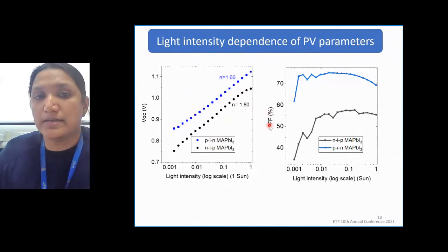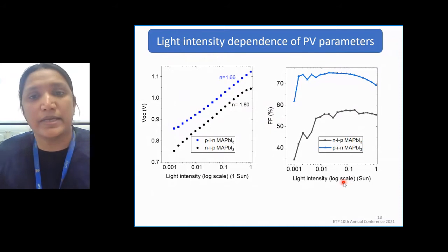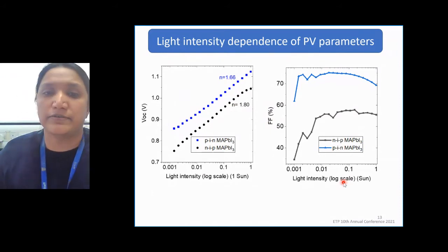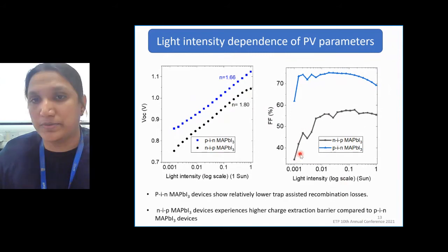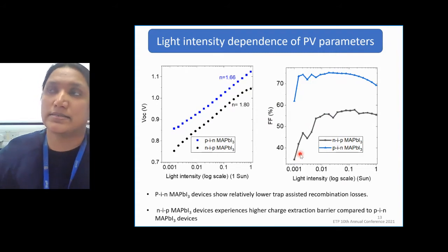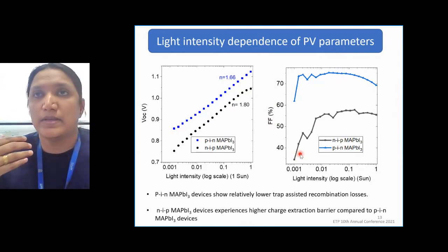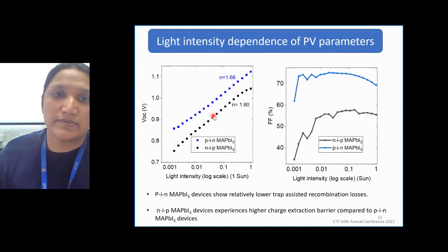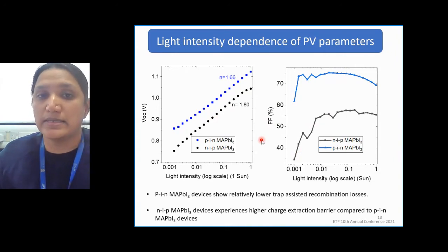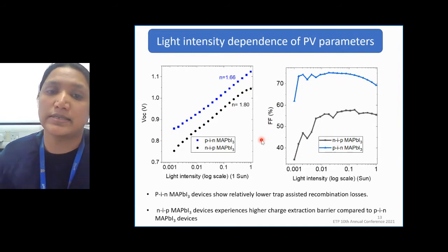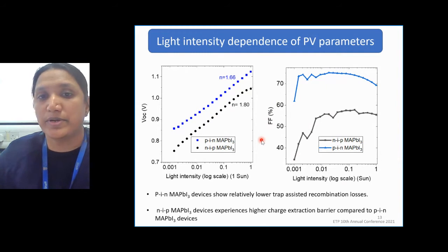And this is further evident from the variation of fill factor with respect to light intensity. Fill factor is a measure of the collection efficiency as a function of light. We can see that for the NIP devices under low intensity, the collection efficiency drops very quickly. So this implies that for the NIP devices, there exists a charge collection barrier, especially at low intensity. When traps are present, as we have seen from this plot, the trap effect will be more pronounced under low intensity, because the incident light intensity is less, so the generated charge carriers are also less, making a barrier for their extraction.